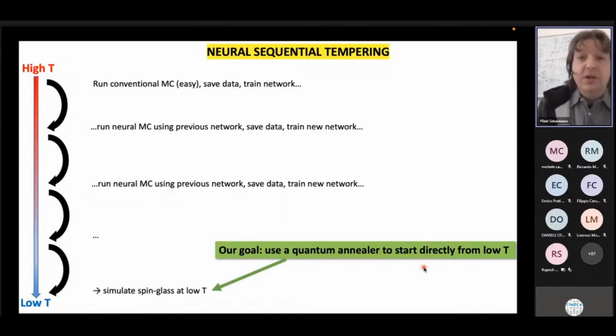Now, what would you do with this neural sequential tempering that I'm mentioning? Essentially, the idea is to start performing your simulation at high temperatures, where even a conventional single spin flip Monte Carlo simulation would work easily. You produce data, you save them, you train a neural network, and then you use this neural network at a slightly lower temperature, and then you run a neural Monte Carlo simulation driven by a neural network. You save more data, you train a new network, and you proceed. And what we have seen is that you can reach the low temperature regime and perform efficient simulations of spin glasses at low temperature.